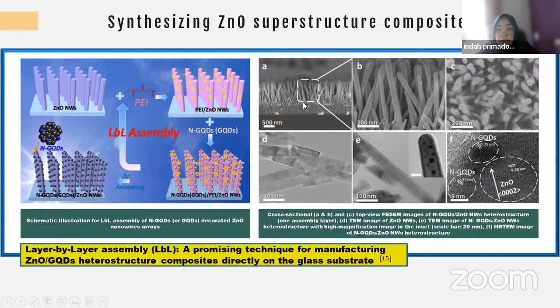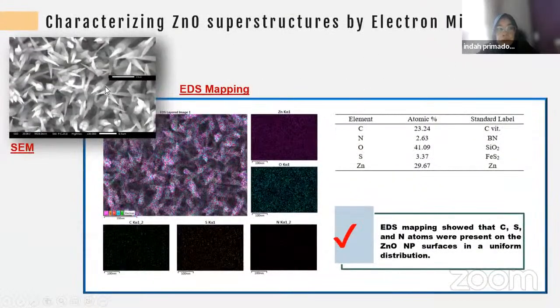So you can see here, we can analyze this using the SEM, but you can see here the TEM image. You can see where the carbon quantum dot is positioned in our prepared one dimension nanomaterial. You can see the black dot here is the carbon quantum dot or organic material here. So here we synthesize successfully the nanopencil, and we analyze using SEM.